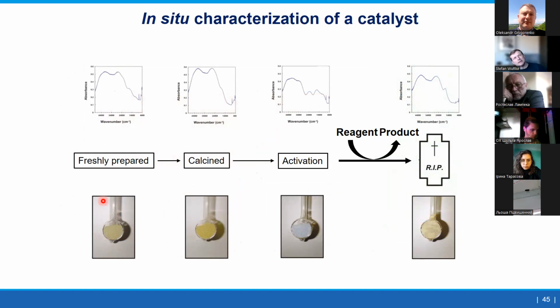It's how material characterization normally happens for a catalyst. What we do is, imagine you have a catalyst with IR. So we have a freshly prepared catalyst here. Then what we're doing is calcinating it. We activate it. You always have an activation, and then we do the reaction, and then the catalyst is dead. And with IR we can measure each of these stages. So we can measure it here, here, here, and here.